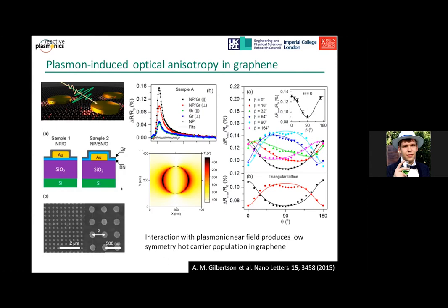However, everything changed when the plasmon resonance is excited in the plasmonic dots here. In fact, the strong coupling between the plasmonic near field and graphene through interband absorption gives rise to the hot carrier population in graphene, which has symmetry lower than the symmetry of the lattice itself. In fact, the symmetry mimics the symmetry of the plasmonic dipolar mode rather than the symmetry of the structure. We have shown that in agreement with the theory, this long-lived anisotropy, which is created as a result of this, is not dependent on the structure itself or its relative orientation to the light, and only dependent on the relative angle between the polarizations of pump and probe.